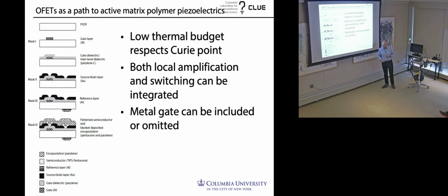So what's my solution? My solution is to add transistors. And this is an old idea, but it's one which I think organic field effect transistors really enable. And basically, here on the left, I show a simple process where we make an organic field effect transistor. And it might look upside down, and that's normal for thin film transistors. But basically, we have a gate here on the bottom. We have a gate dielectric, source and drain semiconductor. And then, if you apply charge here, you can either accumulate or deplete the channel. And that can make a device. So that's one type of transistor.